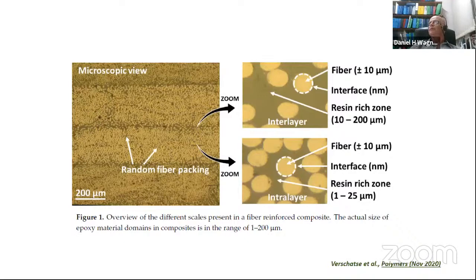The relevance to very thin areas of epoxy or polymers in general in a composite is indicated here. In this case, you have an interlayer between fibers. Those fibers, I think, are glass fibers, so they are of the order of 10 micron. And there is a very thin nanometer scale interface. And this interlayer is somewhere between 10 and 200 micron. But if you have a well-compacted composite, then this zone is very thin, and here it's indicated, this is from that paper that I just mentioned, it's between 1 and 25 micron, but actually it goes much smaller.